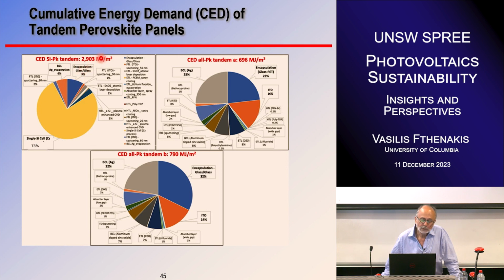And here you have a different functional unit. It's actually primary energy, megajoule per square meter. Before it was electricity only. Again, when you have tandem, perovskite to perovskite, you have less primary energy because you save the crystalline silicon. If you're using the glass and PET as the back sheet, you're using less energy than if you have glass. Okay.